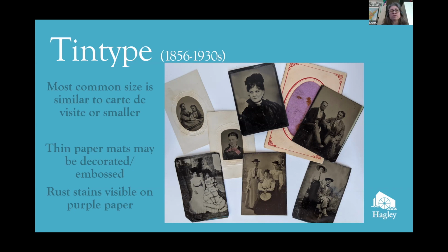Most tintype photographs are commonly taken with a commercial background or furniture or other supports for the people to prevent them from moving around during the exposure. Tintypes may suffer from rusting of the metal plate, and if the plate becomes bent, the collodion may crack in that area. If the corrosion is underneath the image-bearing collodion, the image may crack itself and lift away.